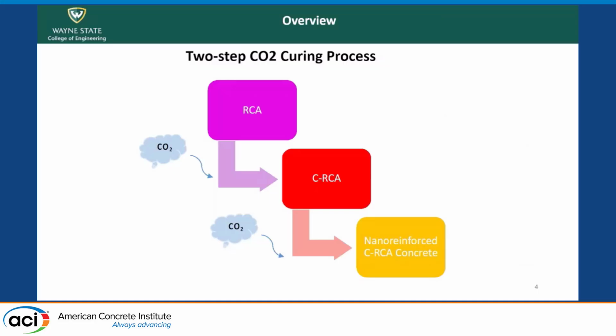This is the overview of the experimental process that we used in this research. We used recycled concrete aggregates. The first step was to implement CO2 on recycled concrete aggregates, or RCAs, and we produced CRCAs, which are carbon-treated recycled aggregates. Then we used these CRCAs to manufacture nano-reinforced concrete, and this went into a second carbonation process inducing CO2 to study the potential enhancement of CO2 capture of concrete.